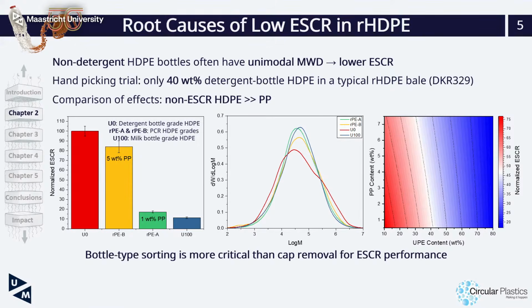But milk bottles are not going to be in contact with surfactants, so they don't use HDPE grades that have this high molecular weight distribution, so they do not have high ESCR. But during recycling, we mix all of those bottles together. A hand-picking experiment by one of our colleagues also showed that in a typical recycling stream, only 40% of HDPE bottles were detergent bottles. When we compare the effects quantitatively using design of experiments, we see that the negative effect coming from the difference in molecular weight distribution is larger than the PP contamination effect.